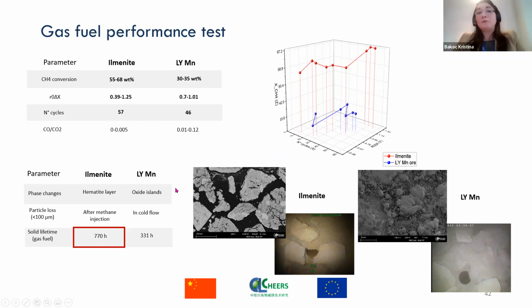Finally, if we look more closely at the morphological changes of the material during these tests with gas fuel in a very highly reducing atmosphere, we can see certain phase changes in both cases. So both ilmenite and LYMN have a tendency to agglomerate, which would indicate that this could not be avoided in a large-scale operation, but the formations are different. So in the case of ilmenite, we can see a form of hematite layer on the surface, and in the case of LYMN, certain oxide islands are noticeable on the surface of the material. And if we take a look at the attrition capabilities, ilmenite would see some loss of the particles that could be collected at the outlet of the carbon stripper.